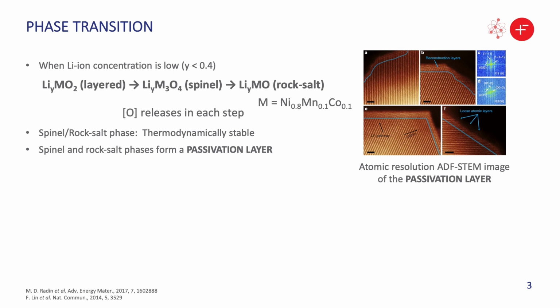Now, what is the structural reconstruction of NMC electrodes? As we mentioned in the previous slides, whenever the lithium-ion content in these electrodes is very low, the transition metal layer goes through a phase change. The layered transition metal layers of NMC electrodes change phase to produce spinel and rock salt layers, and these layers are disordered in nature. However, this phase transition is thermodynamically more favored, and the produced passivation layer also hinders the lithium-ion pathways within the electrodes, which gives rise to the power fade of the batteries.